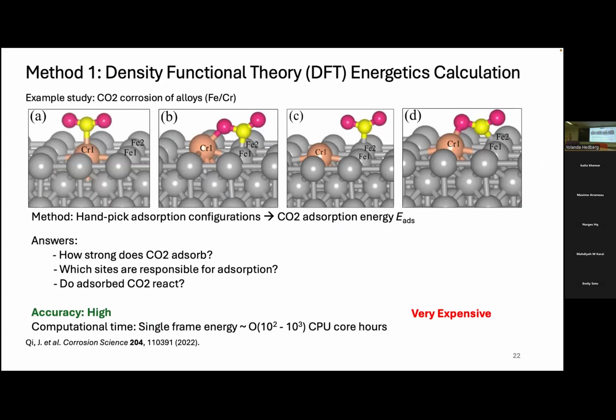So basically there are two different ways of doing these simulations. The first one is the quantum chemistry way of doing simulation using density functional theory. If you think about it in the black box way, you construct different structures like A and B and C and D to represent your local environment in your chromium-containing alloy, and you add the different CO2 into different compositions and calculate the energy for each of them. Every single structure will give you the absorption energy of the CO2, and you can compare if the current binding site for the CO2 is strong, or if chromium is serving as the active site in the alloy.